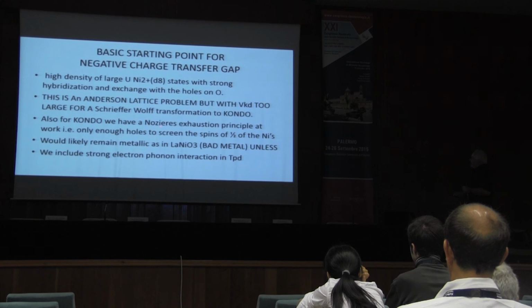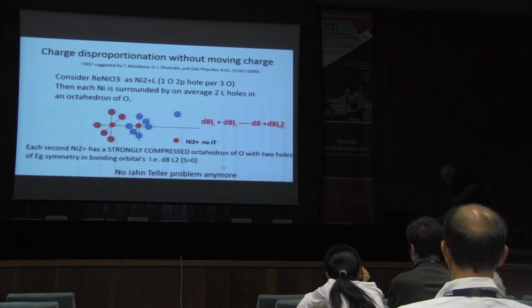Because, remember, that if the nickel is in a d8 state and it has a spin of 1, but it has only given 1 electron, or 1 hole, to the oxygen band, there's not enough there to screen all of those nickel spins. It would likely remain metallic as lanthanum nickelate, a bad metal, unless we include strong electron-phonon interaction, and that's where I'll come to now, in that hopping integral. So this is really what seems to be happening. So consider, remember, nickelate as nickel 2+ with a hole on oxygen. Okay, let's take the other extreme limit, or starting point.